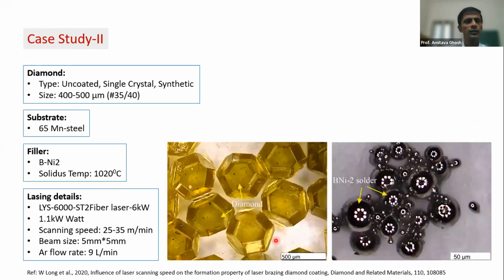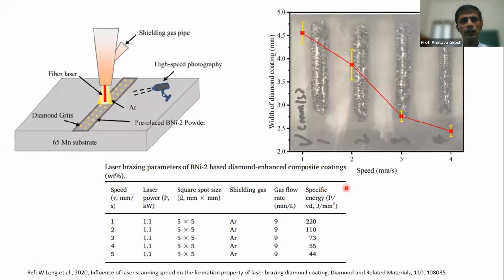So there was another case study with the same alloy. This is with the fiber laser, and the same kind of solder material, nickel chromium. So obviously the chemistry of the joining is the same, what I expected or what we explained during the brazing under the high vacuum and resistance heating technology. Now here you can see they just wanted to make a cluster of diamond along a certain width, and this is just by changing the speed.